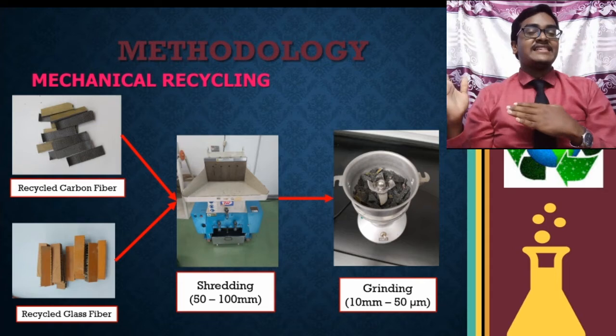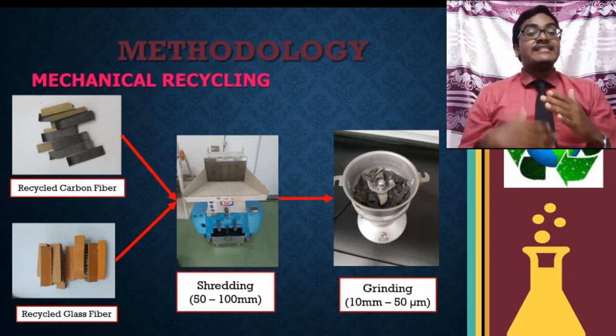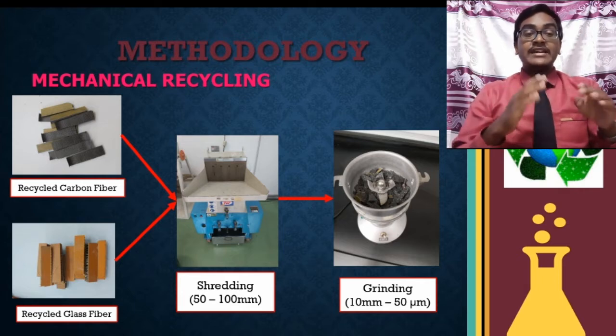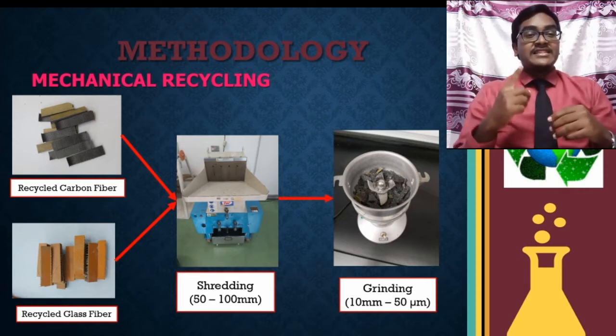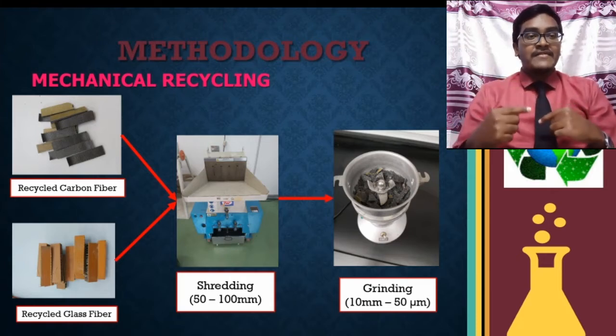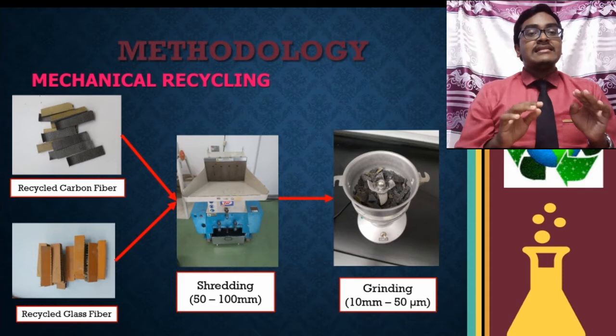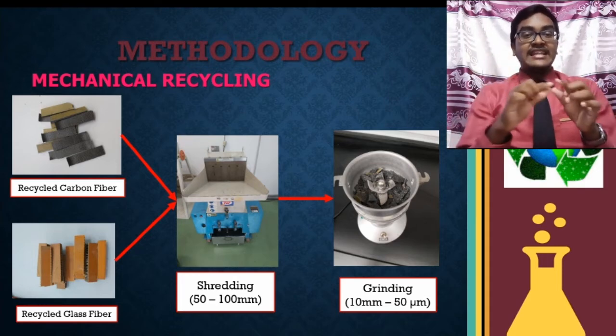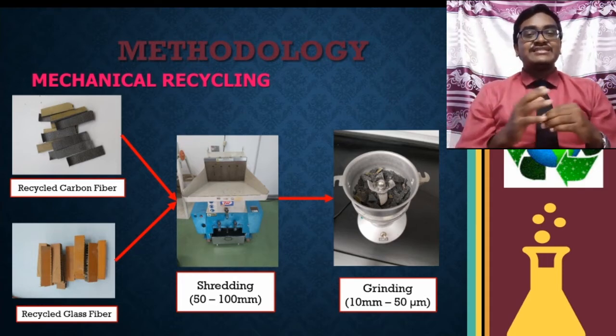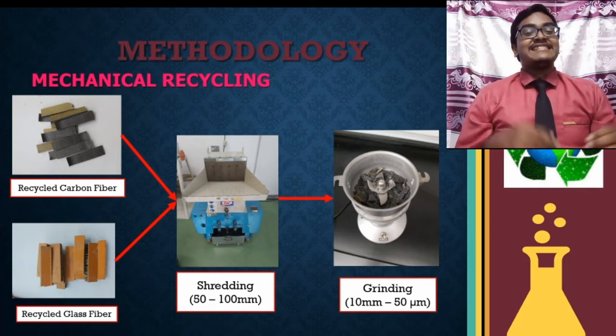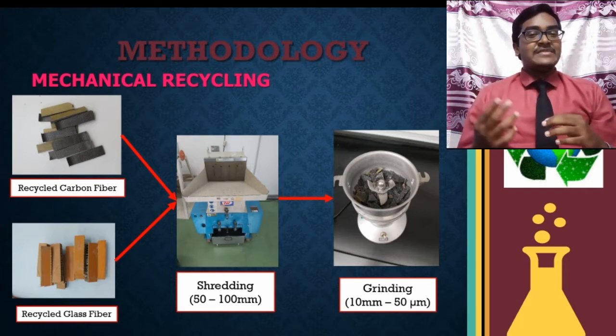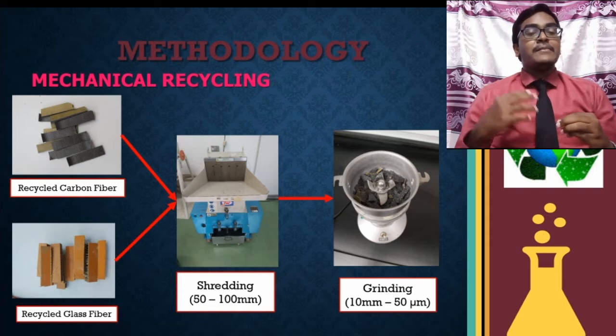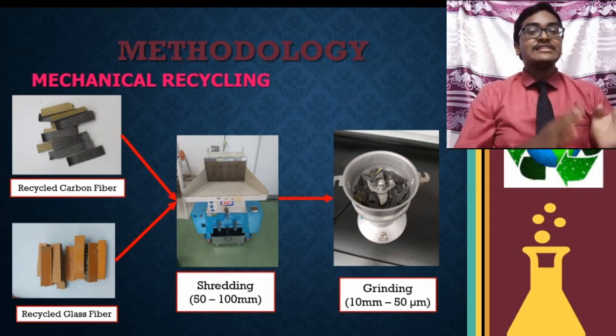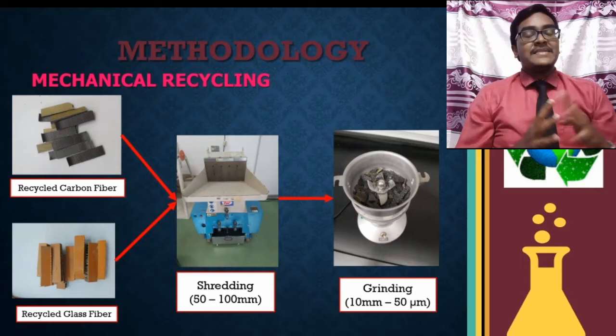Okay, now I'm going to explain mechanical recycling. As you can see, there is the recycled glass fiber and recycled carbon fiber. So cut the recycled glass fiber and carbon fiber into small pieces. The first step is shredding. Shred the recycled glass fiber and recycled carbon fiber composite material into 50 to 100 mm small pieces using a shredding machine. Okay, next is the grinding process. Using the grinding machine, break down the material into 10 mm to 50 micrometer pieces.